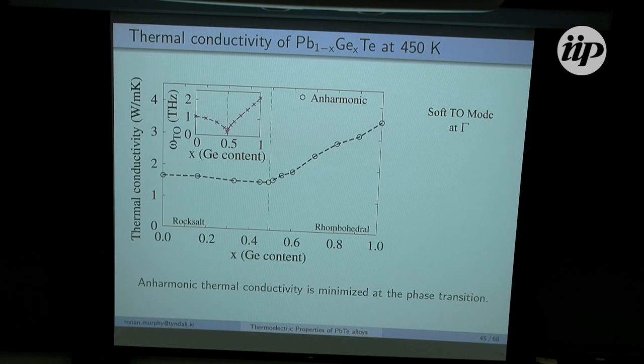So now moving on, I've talked about it quite enough. I want to show what happens to the thermoconductivity as a function of alloy composition. And again, just to remind you, I'm showing here the results at 450 Kelvin, because this is where we expect our model to be most representative of the real world. So this black curve here is the thermoconductivity due to those three phonon interactions only.